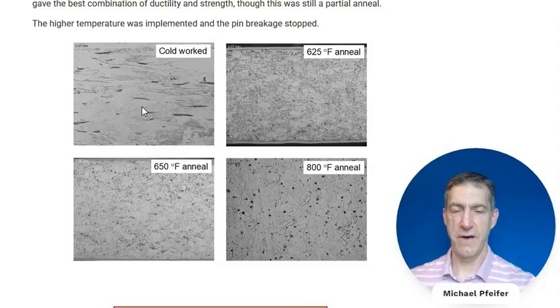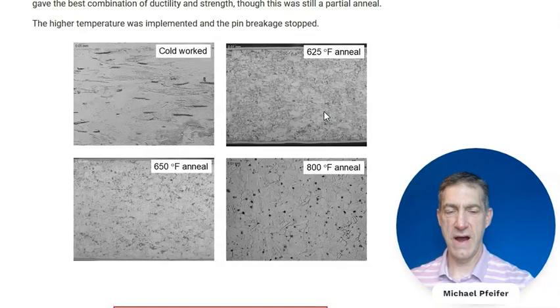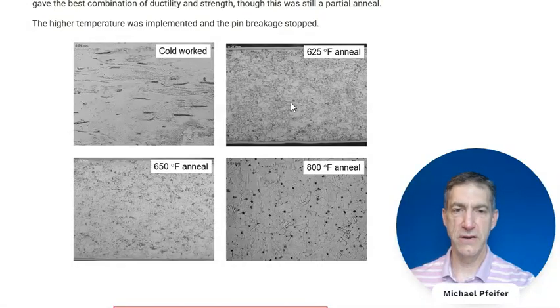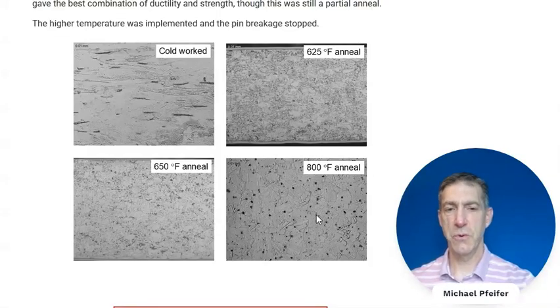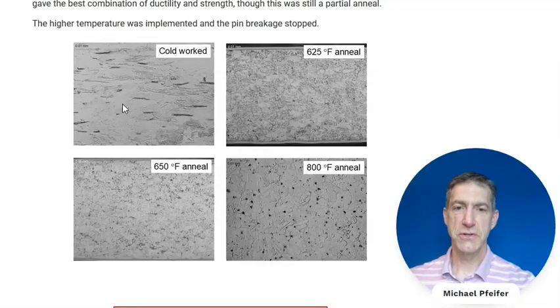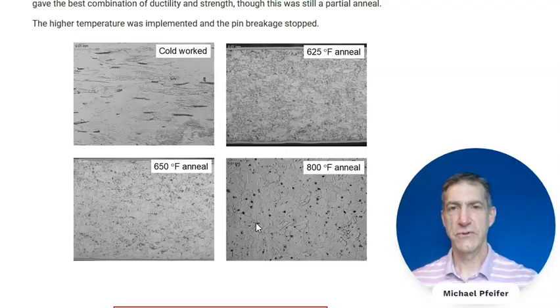This is the micrograph of the metal in the cold work condition. This is the wire in the cold work condition. This is the wire after 625 degree Fahrenheit anneal. And we see that there's still some of the cold work grains here, indicating that it's a partial anneal. At 650 degrees, there is a full anneal, so there's no longer any cold work grains. At 800 degrees Fahrenheit, the grains are even larger than at 650 degrees, which is what we would expect with a higher temperature anneal. So this progression in changes in grain structure is expected as we increase the annealing temperature.